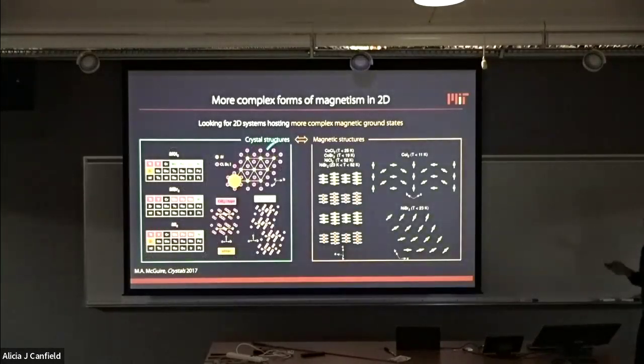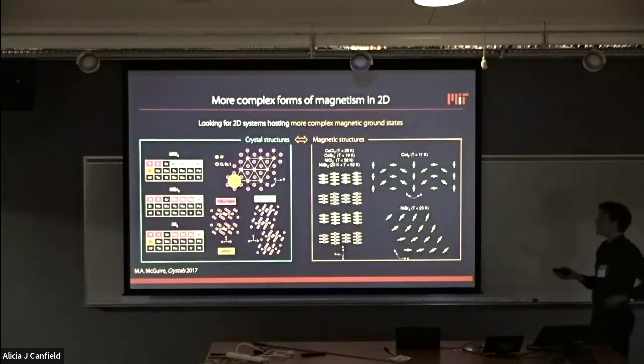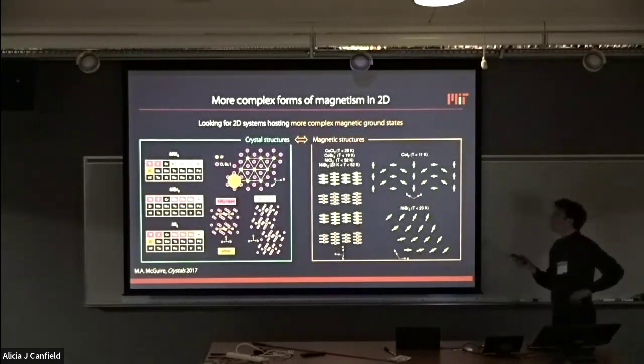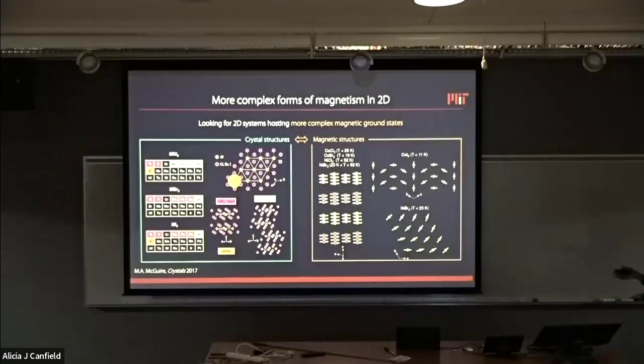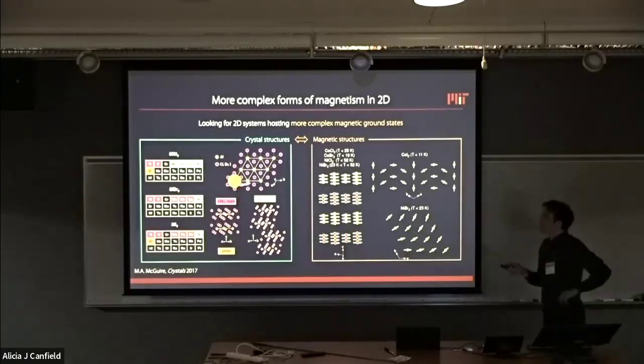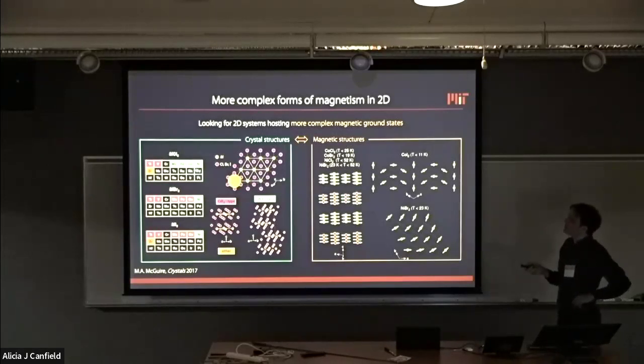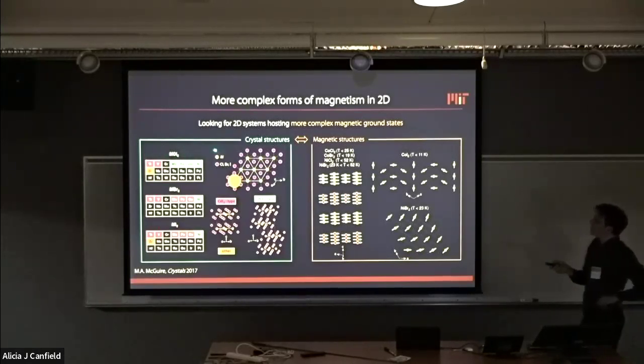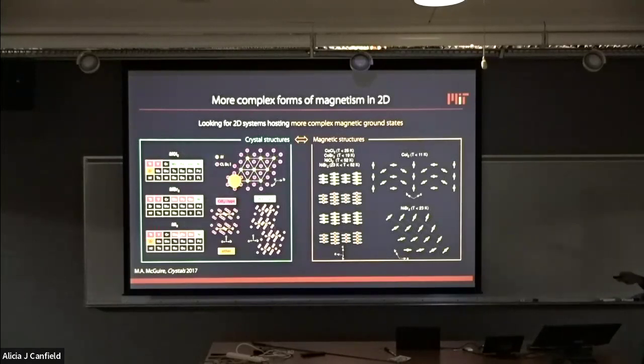So we look for kind of the wide registry of van der Waals magnets. And there's in particular the class of transition metal dihalides, which is very rich, also the trihalides. But the dihalides are 2D magnets, insulators, they're charge transfer insulators that have very simple chemical composition, metal, halogen 2. So you can form them with chlorine, bromine, and iodine. There's a lot of A-site metals that you can put there.